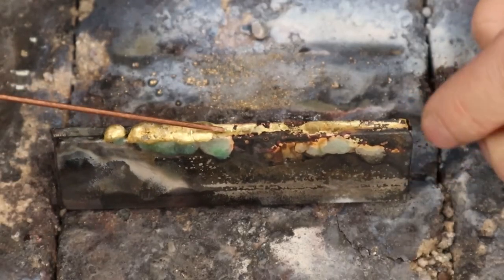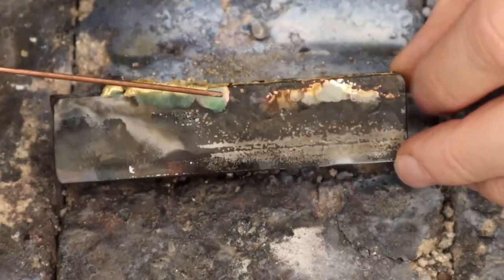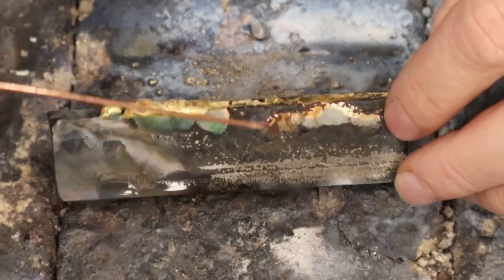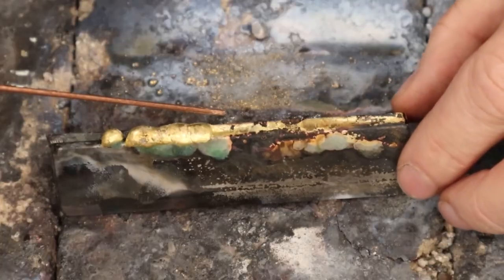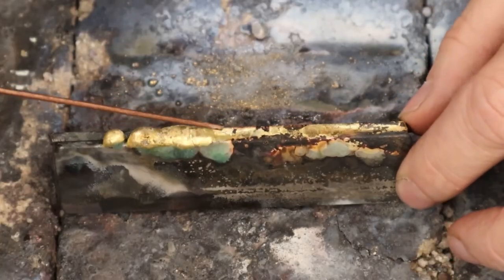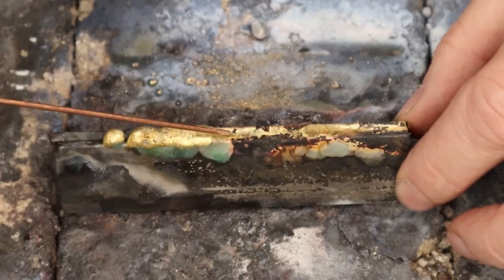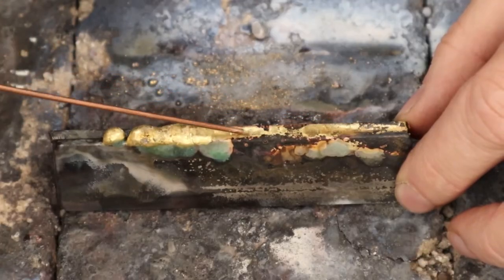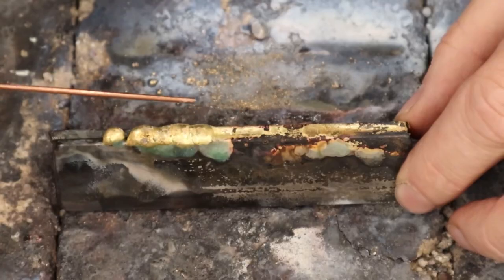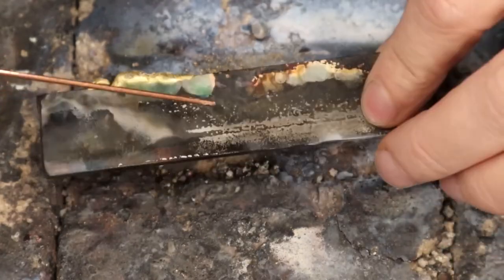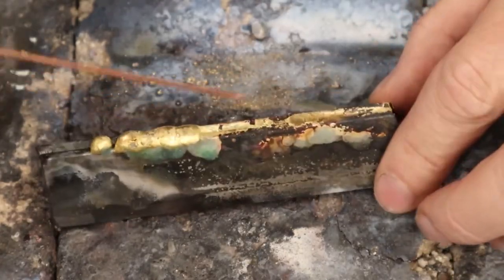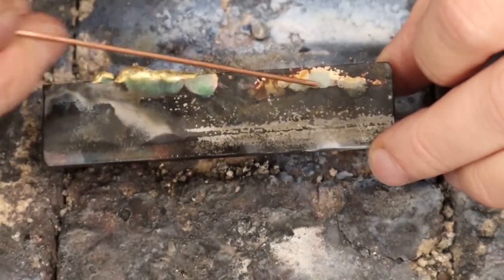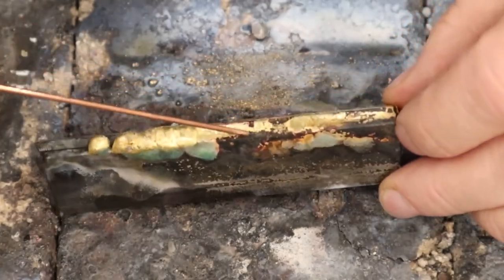Now when we look at the other side that got too hot, first off, I can see burnt oxides all over the place. While I was doing it, the flux was burning off like crazy. And there is no hump. In fact, I can see the seam between the two pieces, so there's a loss of strength in there because there's just literally no brass. And none of the flux is left available. It's all just been burnt away, and you can see all the extra oxides.